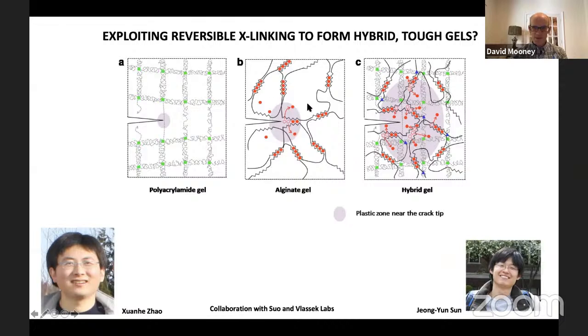Now, in contrast, we have something like an alginate that is reversibly cross-linked and can dissipate energy because it's viscoelastic, in that some of that energy would be taken up by decross-linking. Now, these gels, though, because they're formed from relatively weak bonds, don't absorb a lot of energy. But what they proposed is if they combined a covalent network that could transfer energy over significant distances with this ionically cross-linked network that could dissipate the energy, this would create a large zone that would be absorbing energy, dissipating energy, and really toughening the material.